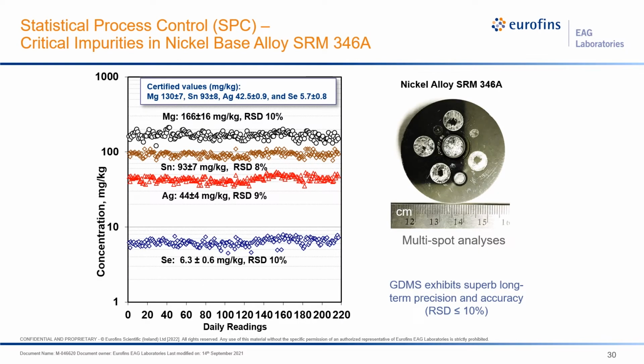At EAG, how do we do this? We start with statistical process control of our instrument using a nickel-based alloy, SRM 346A. We run the sample every day to ensure our instrument is within valid status of analysis. Here shows you the SPC chart of this alloy standard. It covers element impurity concentrations from less than 10 ppm to 166 ppm, and those are all certified values. As you can see, over the 220 days of readings, the variation is typically within 10% for all those elements shown here. This demonstrates GDMS is an excellent tool for production support.